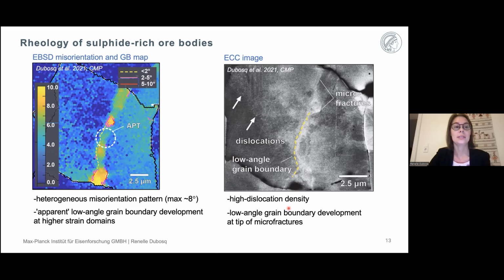And so here for this next step of the project, I wanted to select a highly deformed region of interest within the pyrite crystal to be able to look at the interactions between fluid inclusions and other crystal defects within the mineral. So in this EBSD misorientation and grain boundary map here, we notice that there is evidence of crystal plasticity in this sample, in the form of a heterogeneous misorientation pattern with maximum misorientations of 8 degrees, mostly localized in the center of this grain, and apparent low angle grain boundary development in these higher strain domains here.